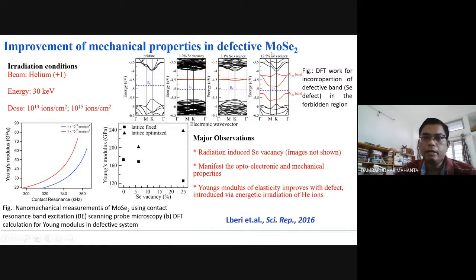So improvement of mechanical properties in defective MoSe2 was reported by these particular groups in Scientific Reports. You could see that there is a drastic improvement in Young's modulus. So you could see this red one is at higher dose, having fluence 1 into 10 to the power 15 ions per centimeter square, and this is 10 to the power 14 ions per centimeter square. So when this material MoSe2 is irradiated with helium, +1 helium with energy 30 keV, then one can increase Young's modulus. So toughness increases because of the presence of defects.